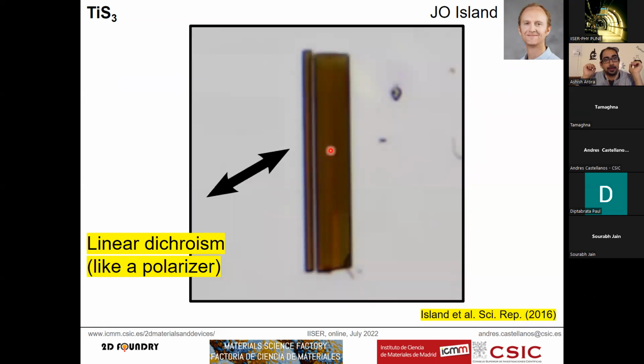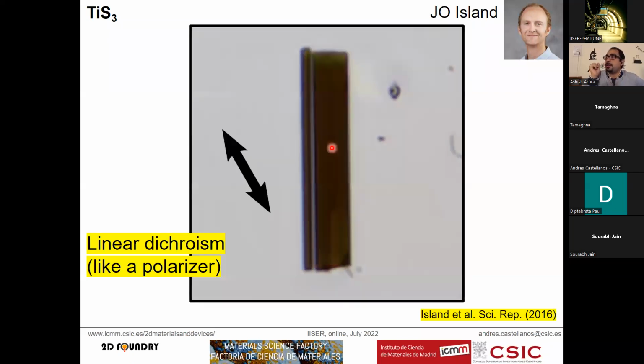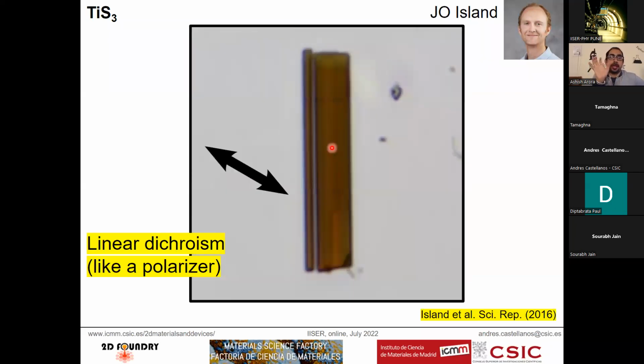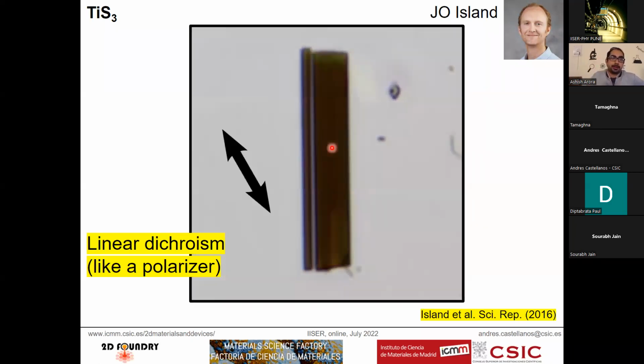No, I'm remembering now. So we have done these measurements, and we have calculated the refractive index and extinction coefficient as a function of the polarization angle. We have one old paper about birefringence and dichroism in titanium trisulfide. Yes. I see. No, this is interesting because compared to, for example, ReSe2 or ReS2, there the band edge shifts only by a few tens of meV if one goes from one polarization to the other. It seems here the effect is much larger. Yes.